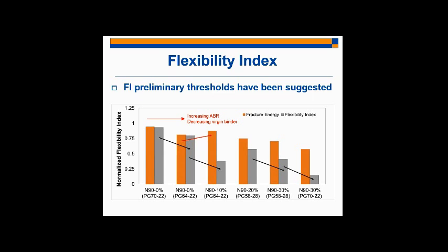First, the fracture energy seems to make a jump from this N90 0% PG64 minus 22 mixture to the N90 10% PG64 minus 22 mixture. So all things are held constant between these two mixtures except for the addition of 10% asphalt binder replacement, which is 2.5% RAS. So we can all agree that the addition of this 10% asphalt binder replacement, or 2.5% RAS, would result in a lower resistance to potential thermal cracking. So if I'm using fracture energy as my distinguishing criteria, it's misleading, right? Because I'm getting a higher value for the fracture energy for the mixture that I would expect, and that's proven to behave more poorly under low temperature cracking conditions. And so this is a very concerning observation that we've made using the fracture energy as the criteria.